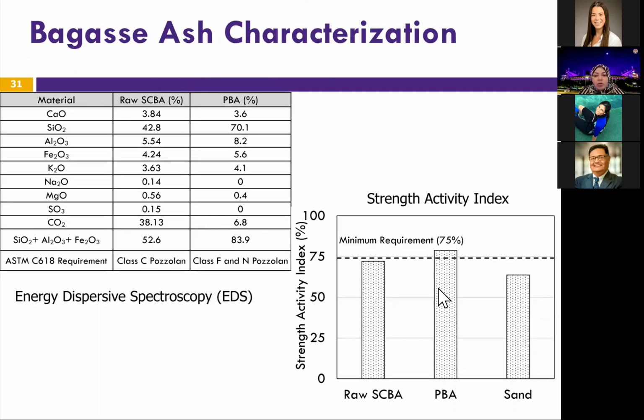Okay, so we also analyzed the composition of the raw bagasse ash and the processed bagasse ash using EDS. And as you can see from the analysis, the raw bagasse ash is mainly composed of silicon dioxide and carbon. Of course, the carbon comes from unburned sugars. But if you look at the pozzolanic components, which is the silica oxide, the aluminum oxide, and the iron oxide, in the raw bagasse ash, you get 52.6%, which makes it classified as a class C pozzolan according to ASTM. And for the processed, it increased to 83.9%, which means it can be classified as class F or N pozzolan, which is great. So that means the bagasse ash is not only something that can be used in ECC, but it also can be used in concrete as a cement replacement.